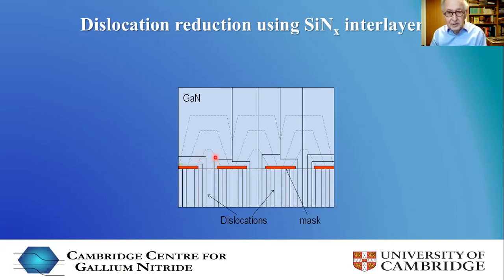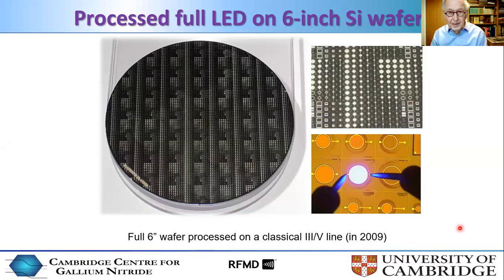Next slide please - I'm sorry, this is one of the slides I had to reduce, so I'll just tell you the results. We can reduce the dislocation density by 2 orders of magnitude using this method, going from something like 10 to the 10 dislocation density down to 10 to the 8. And at 10 to the 8 density, we have brilliant light emission.